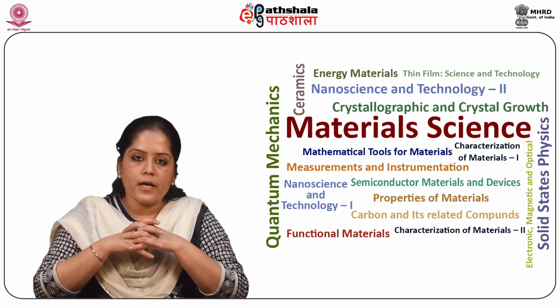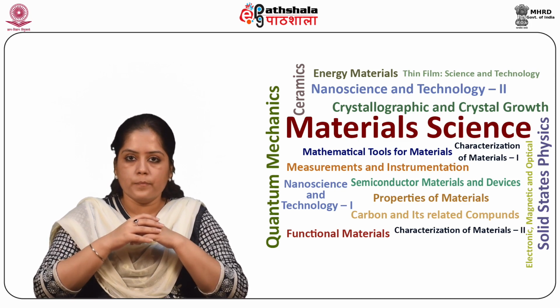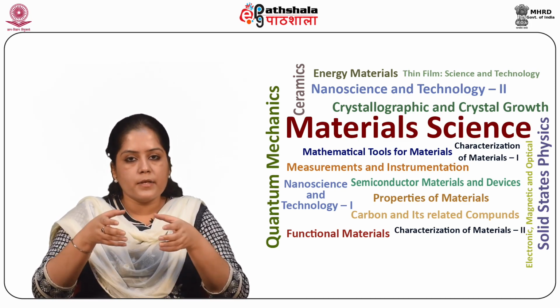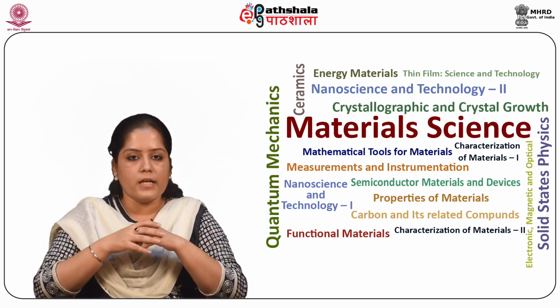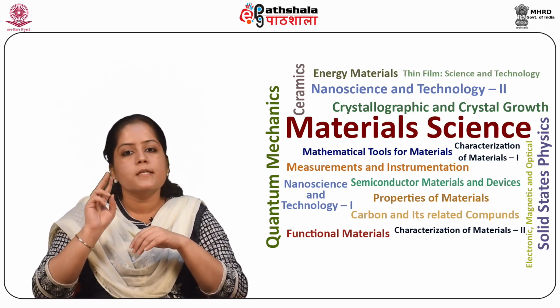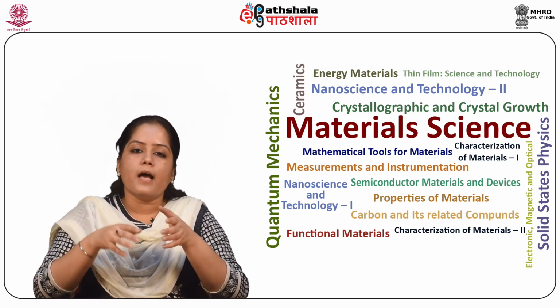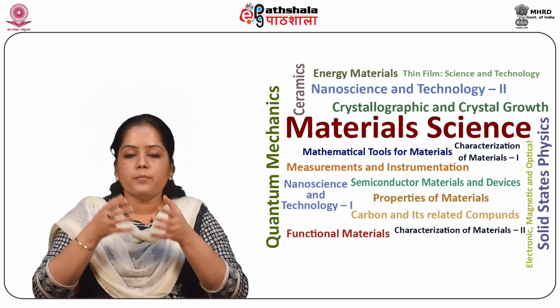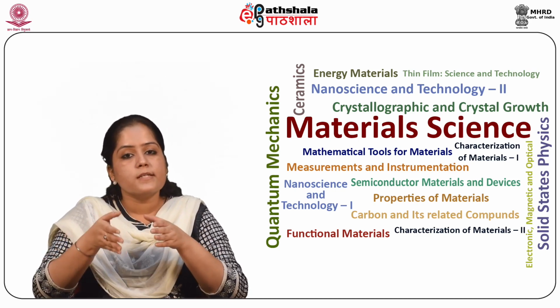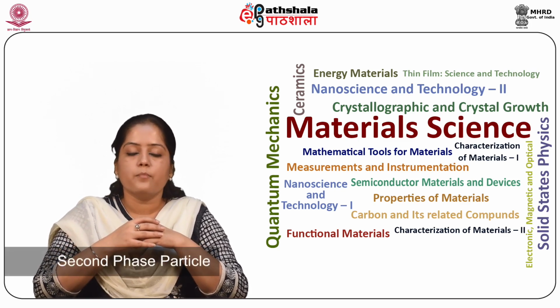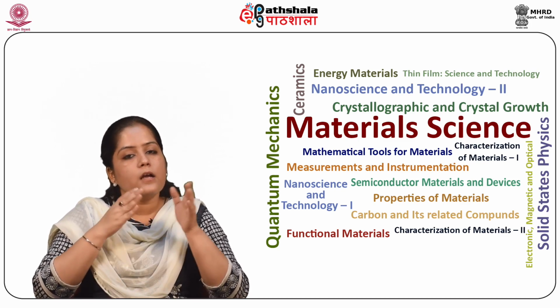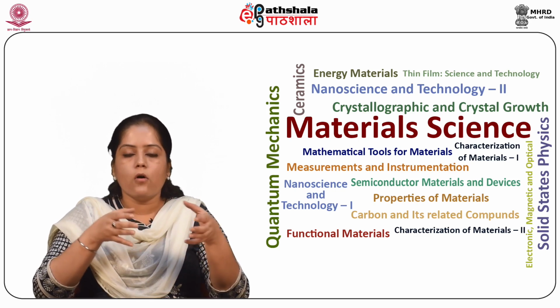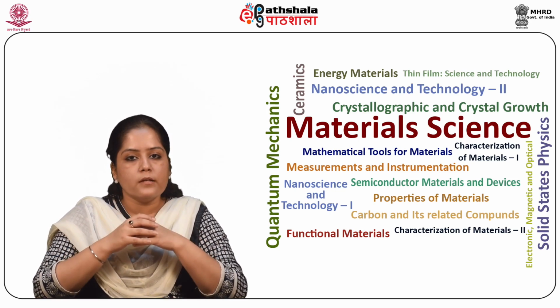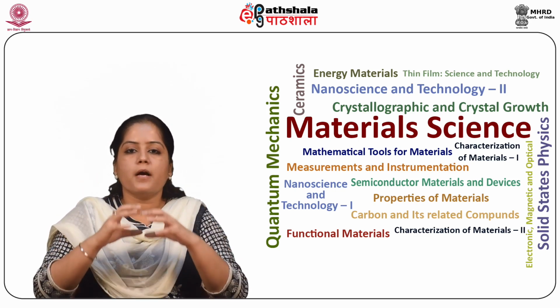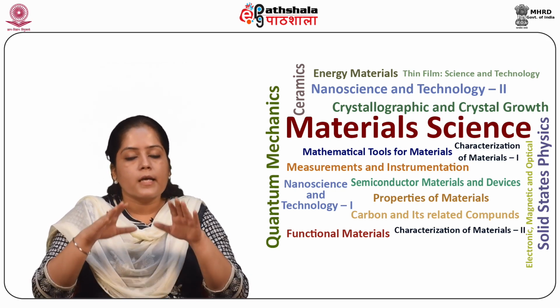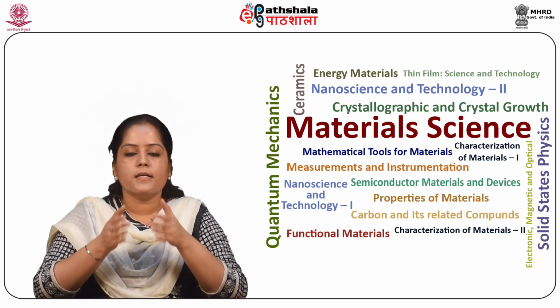So students, let us summarize what we have learnt in this module. First, the toughening mechanisms in ceramics can be categorized broadly into the following categories. First, the crack tip interaction. Second, crack tip shielding. And third, crack bridging. Next, we discussed that crack tip interactions occur when the crack tip approaches an obstacle such as a second phase particle. The crack can continue to move by bowing between the obstacles, or it may get deflected. In crack bowing, the crack goes around the particles and then joins back again. The particles remain unbroken. Calculations show that this leads to an increase in the fracture toughness.